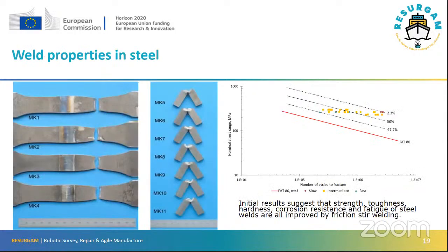In terms of the weld properties, those are very good. On the left-hand side of this slide, you'll see some tensile test pieces, and all of those have broken in the parent metal and not the weld. So the weld is actually stronger than the parent metal. In the center of the image, we see some Charpy impact test pieces. None of those are fully broken, indicating that the weld was very tough and still had a lot of ductility.